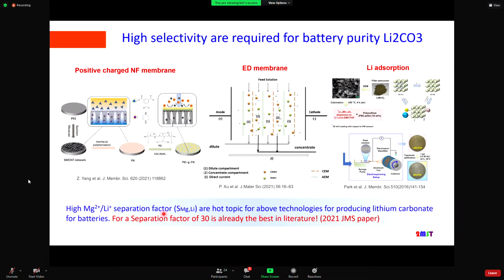The problem for the separation of magnesium and lithium based on diffusion is the purity of the final product, lithium carbonate, which is not high enough for battery use. Commercial nanofiltration membranes have a magnesium-lithium selectivity of below 10. The best published paper in 2021 reached a selectivity factor of 30.